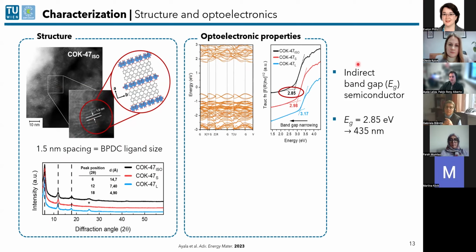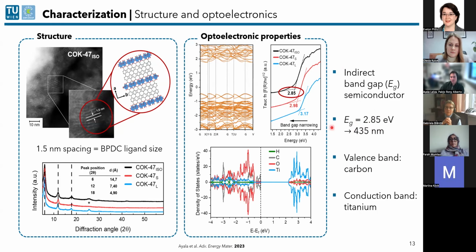So we found out that it's an indirect band gap semiconductor, and that the band gap of COK-47iso was the narrowest amongst all of them, only 2.85 electron volts. This opens up the possibility to use visible light to excite our material. And then also to the band structure, we did some DFT calculations, and we found out that the edge of the valence band is composed of states arising from the carbon atom, and the conduction band from states arising from the titanium atom. So this will be important in a bit.